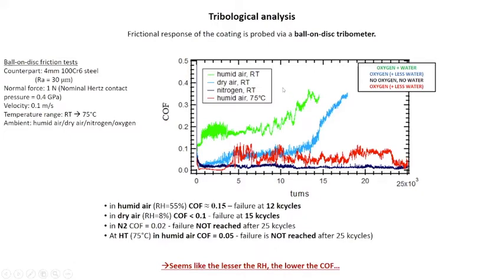Okay, related to the tribological performances, we measured the coefficient of friction as a function of the sliding distance by means of a ball-on-disc tribometer. Here you can see the main characteristics of the test. I just want to highlight the fact that the counterbody is made of steel, 100Cr6 steel, and the ball has 4 millimeter diameter.